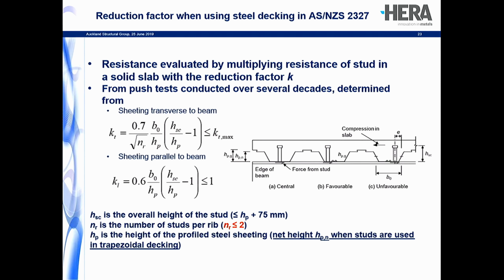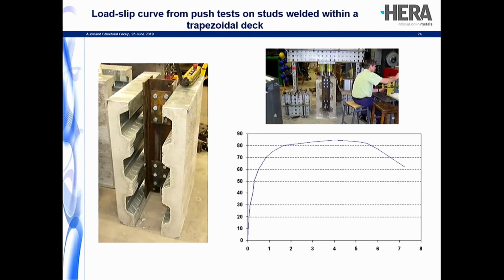And the other thing to note, and this is going back to some work that I'll talk to you about in the next couple of slides that I did in the UK, is that most of these modern trapezoidal decks tend to have this small reentrant stiffener on the tops of their crests, which you can see shown here. And the million-dollar question often is, well, what height of the sheeting do you use in these design equations? Do you use the overall height or do you use the net height? And in 2327, it's very clear that when you're using stud connectors, the net height is the one you should be using. And the reason why, it seems a very, very small nuanced rule about the net height, but believe me, the basis of it involved quite a lot of testing in the UK.